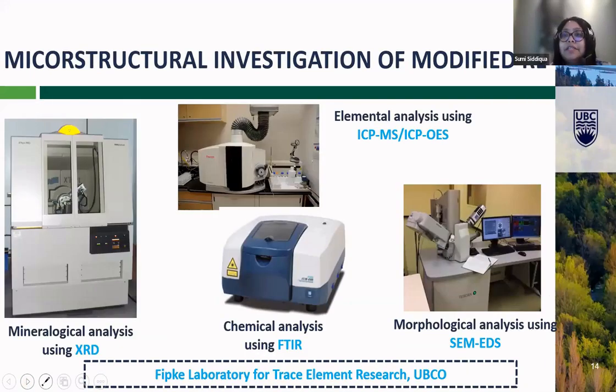Now, looking into the microstructure, we have to do more than the general microstructural analysis. When we make the modification, of course, we have to look into the XRD, the SEM, FTIR, and then the chemical composition and the leaching, so we run the elemental analysis, ICP-MS, ICP-OES, those kinds of tests, and I want to acknowledge those laboratories at our campus for the trace element research.